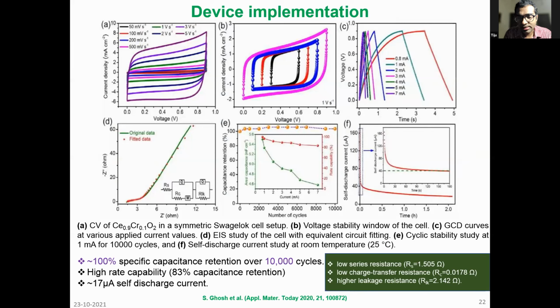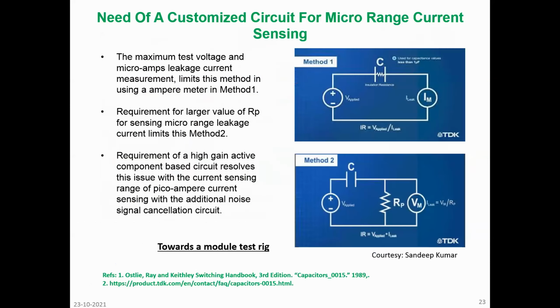What is rather nice is that it has fairly high rate capability. And not only that, this also seems to be fairly robust in terms of its cyclability. Next, please. So 10,000 cycles, and you barely see any capacitance fading. So now what we are doing is we are trying to develop a test rig for this particular system. We are trying to come up with a module that can be built on the devices that we tested in the previous slide. So that test rig is being developed currently. Next, please.